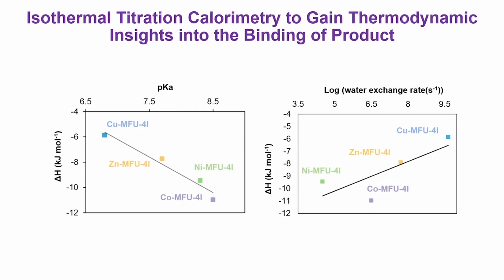The copper does not care about the water, and it does not care about the product either. And that's where Jahn-Teller distortion, if we learn it in inorganic chemistry, comes into play in our favor, because that twisted coordination is actually helping us not to allow that coordination to take place.